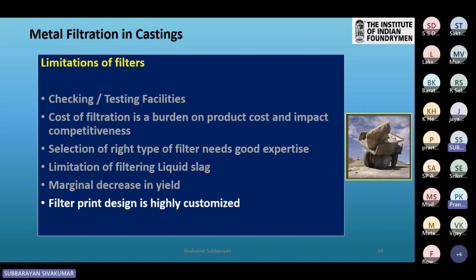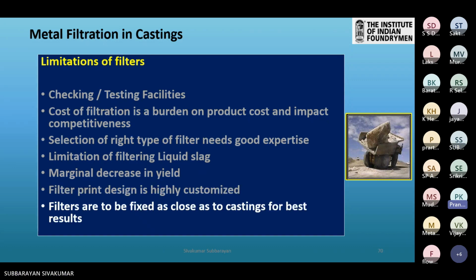Filter print design is highly customized, and it again needs expertise over a period of time to avoid difficulties due to the design of the filter print, and to accommodate effective filters in the running system. Filters are to be fixed as close as possible to castings for best results. This point is very vital. This is a recommendation by many filter manufacturers. But when we practically design our running system, it may be difficult to adopt this technical point due to various practical difficulties like a double pin or core print, or the space in the match plates. So again, it is subjective and varies case to case, and we should adopt the best solution for getting effective filtration.